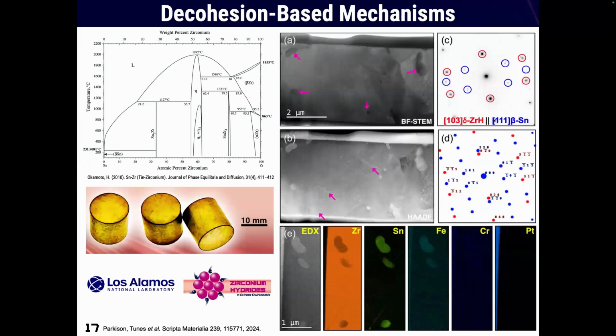With hydrides, we observe a very interesting phenomenon supporting this, in my opinion. You have a zircaloy in nuclear industry, which is a zirconium 1.5 tin alloy. The tin is fully dissolved substitutionally in the zirconium lattice. When you hydride to form the hydride pellet, all the tin goes out of solid solution. So the hydrogen enters in these tetrahedral sites in the sublattice and expels all the solute atoms. It's quite interesting.